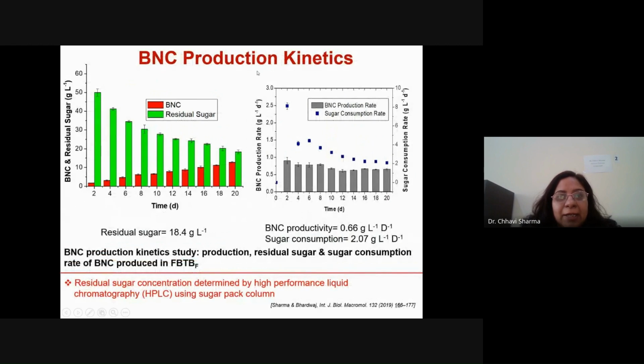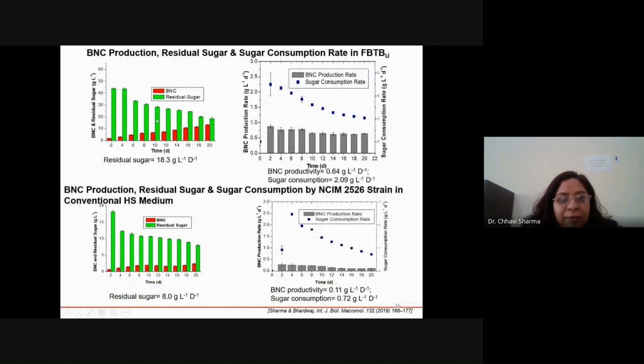The optimum pH is around 3 and the optimum temperature is around 30 degrees. Next, the production kinetics of the BNC was also studied, and it was found that using the freshly brewed fermented black tea broth medium, the BNC productivity was 0.66 gram per liter per day, and the sugar consumption was 2.07. The residual sugar was 18.4. We also tested the yield using the used tea, which is slightly less than the yield we got previously.